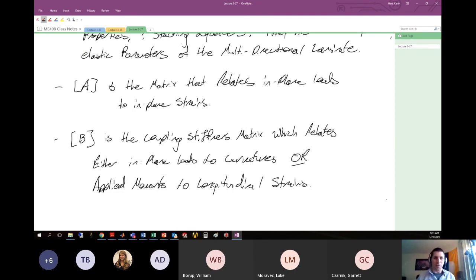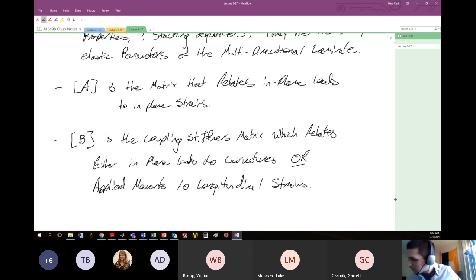The same idea here with laminates is if we pull on the laminate, not only is it going to strain longitudinally, but it might also curve out of the plane or curve the other direction or possibly curve with some torquing sort of curvature as we apply these in-plane loads, just based on the general material inhomogeneity or orthotropic behavior. It's a little bit difficult to wrap your mind around that. So one idea is relating in-plane loads to curvatures. So let's talk about that.